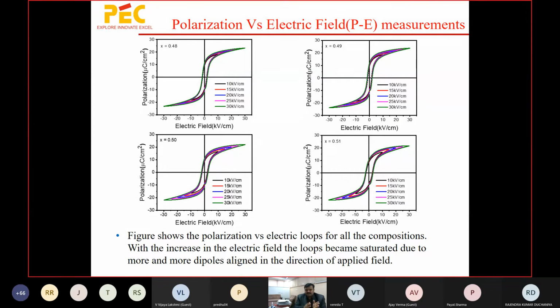These are the plots between polarization and electric field. You can see that in one plot, we change the applied field from 10, 15, 20, 25, 30 kilovolt. You can see that with the increase in the applied field, the polarization versus field plot is also increasing. At lower strength, that is 10 kilovolt per centimeter, you can see the black curve, which is not seen clearly, but its saturation polarization is also very low.